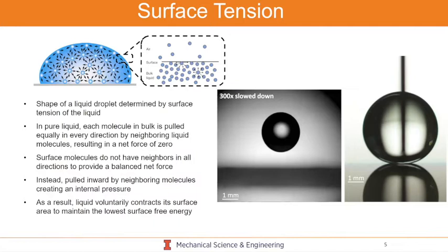And the fundamental thermophysical property of surface tension arises simply because if you think about the molecular interactions of water in a droplet, and here on the top I'm showing a droplet, you can think of these circles as water molecules. The molecules in the bulk have the same interaction potential, essentially, in any direction they look at. They have the same kind of pull or polar interaction with their neighbors. That's not actually true for the molecules which are at the interface. So these molecules on the outside will have an interaction with the bulk molecules on the inside of the liquid, but on the outside of it, they're actually interacting with air molecules or water vapor molecules.